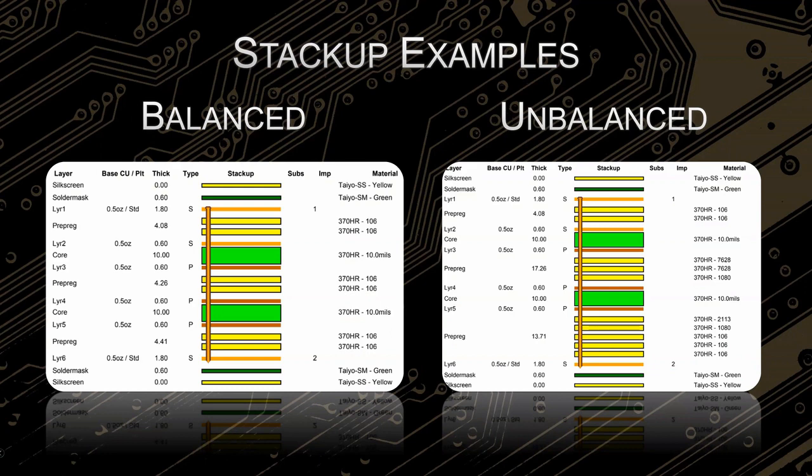So when I define my via plating, let's say I want 1 ounce plating for my vias, that 1 ounce is also going to be added to my outer layer, right? Correct. And if for some reason I wanted 1/2 ounce and not 1 ounce, is there anything to do about that? Our standard is going to be 0.7 mils in the barrel. Okay. So whatever I ask for in my barrel, that's what I'm getting on my surface as well. Yeah, by standard, it's always going to be 0.7 mils. If you want anything more than that, it's going to have to be in your fab print or README notes. And it's as simple as letting us know what thickness you want inside. Okay. Is there any way to plate those vias completely shut? To an extent, yes.